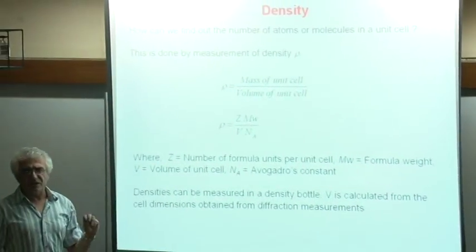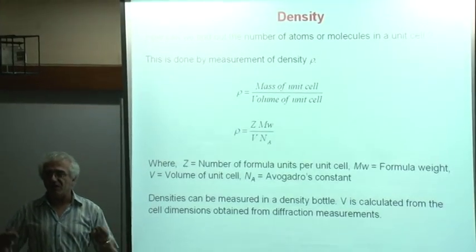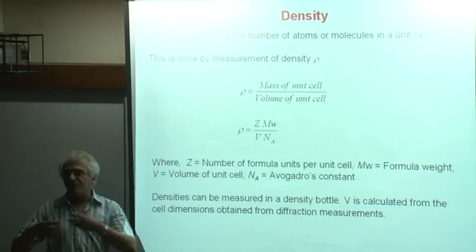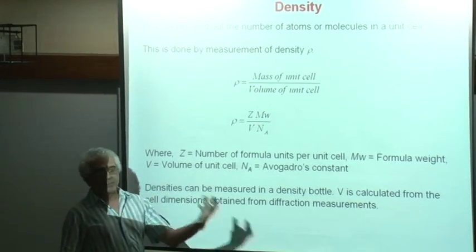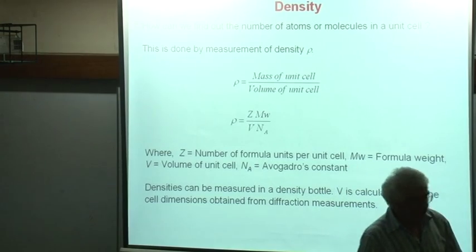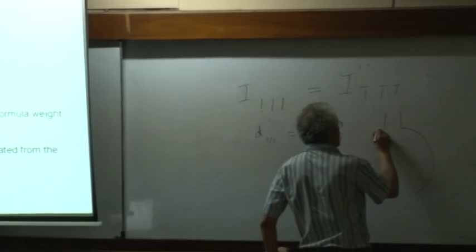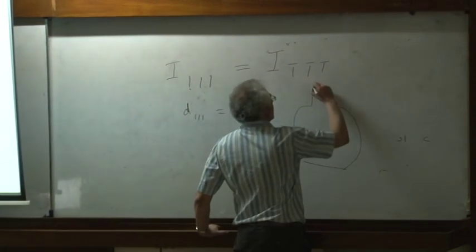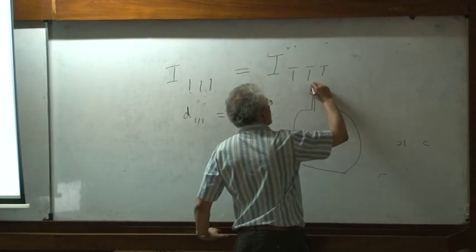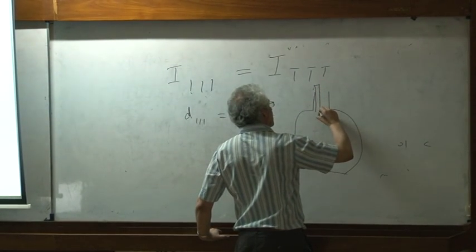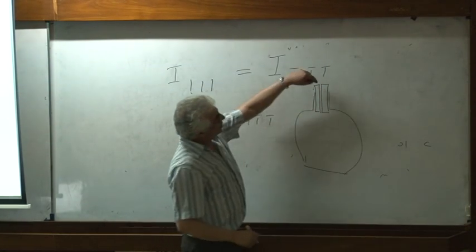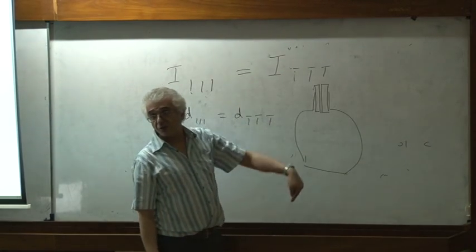And we can measure density. Density can be measured in a number of ways. Usually people use a variation of the Archimedes method. So displacement of some fluid. That fluid can be a liquid. So you can use something called a density bottle, which is basically a little bottle of known volume with a stopper, a ground glass stopper, and the stopper has a tiny hole through it.